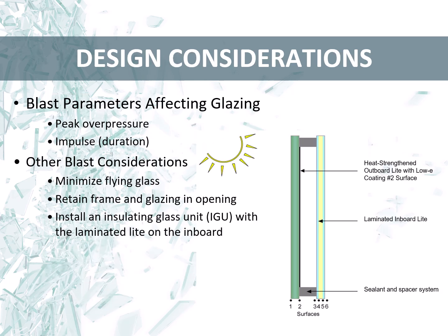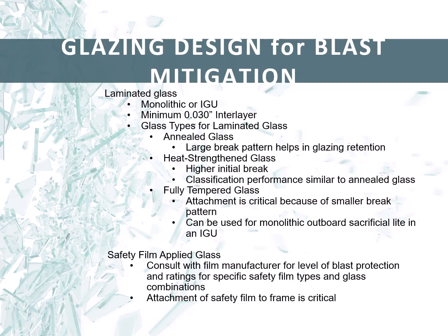Basic information, such as the peak overpressure and impulse or duration of the blast, is required to design a glazing system. Other considerations are the ability of the glazing to minimize flying glass and keep the window system integral even if the glass is cracked or broken. When insulating glass units are specified for energy performance, the laminated light should be positioned on the inboard of the unit. Laminated glass can incorporate annealed, heat-strengthened, or tempered glass with a 30 mil or 60 mil interlayer that bonds the glass together.